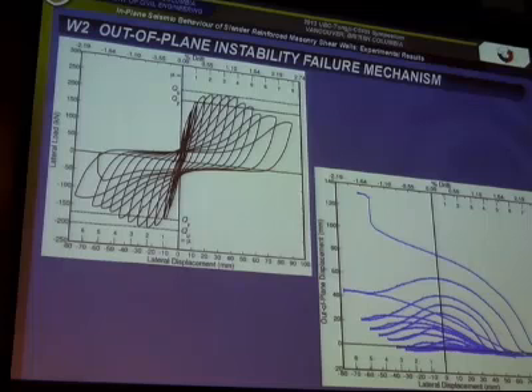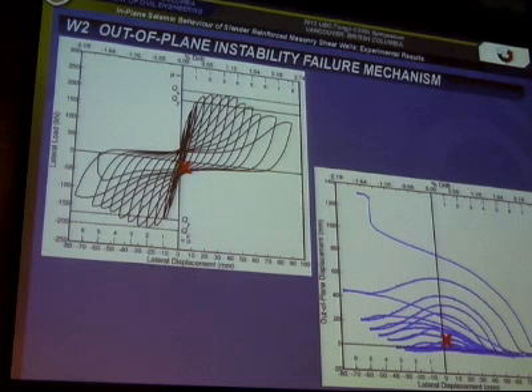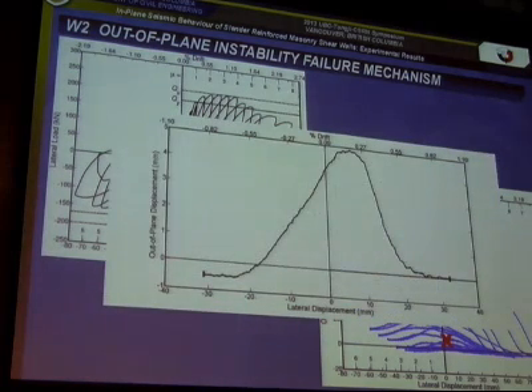Looking specifically at the mechanism itself, we can see that very early on we had the out-of-plane displacements greater than anything seen in the first test, which were on the order of around 5 millimeters. And as you can see, very soon after load reversals, when you get these large out-of-plane displacements developing, they continue until you get the face shells coming into contact, upon which the restoring moment causes these displacements to decrease again.